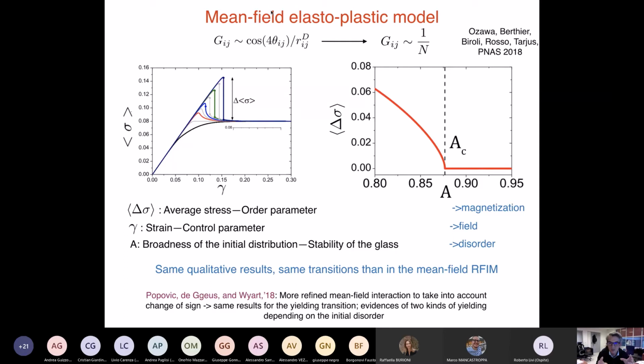And so the mean field theory is really the same, in the sense that if you study, for example, the critical exponents within mean field theory, at the critical point that separates the 2 phases, the continuous behavior from the discontinuous behavior, these are the same. Having the same exponents within mean field theory is not so constraining, but you can study also other quantities, and really you find exactly the same physics as in the mean field version of the hysteresis of the random field Ising model. So this is, I think, the first interesting result on this problem. Of course, we made a big approximation doing mean field theory, I would say two big approximations. The first one is to say that the system is mean field, meaning that we take an interaction from everybody to everybody else.